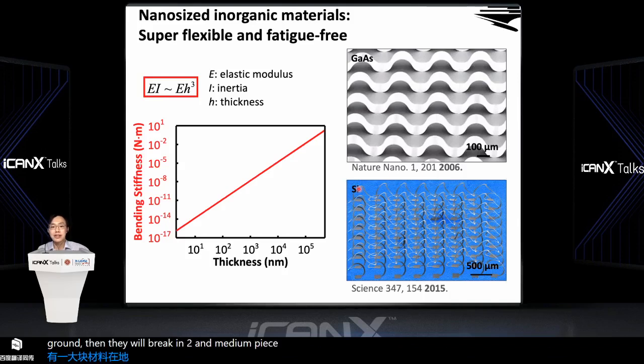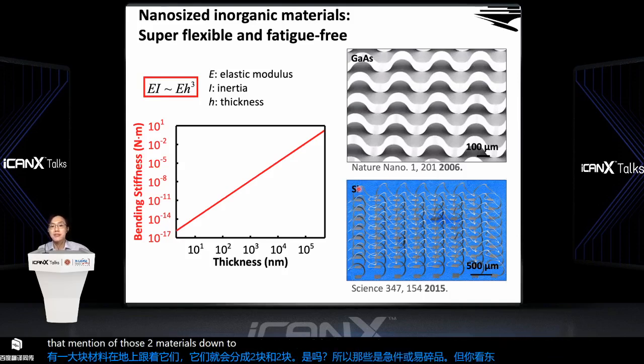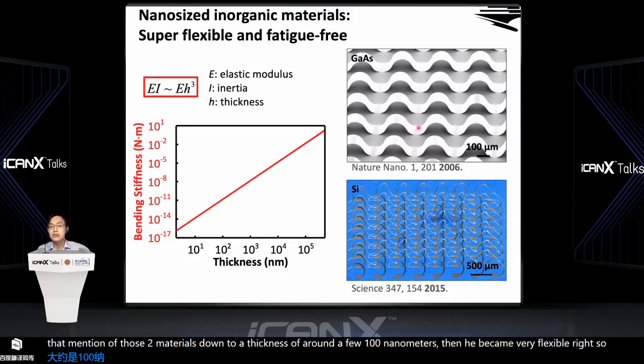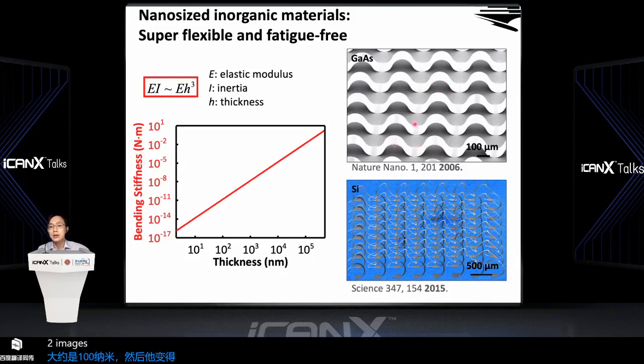So those are very fragile materials. But when you reduce the dimension of those two materials down to a thickness of around a few hundred nanometers, then it becomes very flexible, right? So those two images represent two typical examples of this controlled buckled nano ribbons.